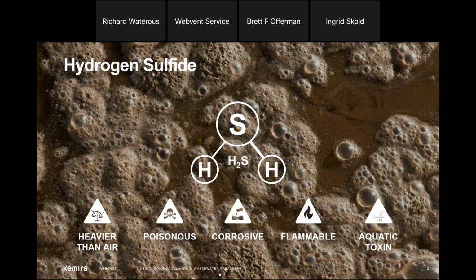When H2S reaches elevated levels, concrete corrosion rates can be approximately 1/2 inch per year. Many municipalities have encountered catastrophic collection system line failures due to the presence of elevated levels of H2S. In fact, collection system collapses due to H2S origin corrosion are the driver for many municipalities to initially implement a collection system H2S control program.